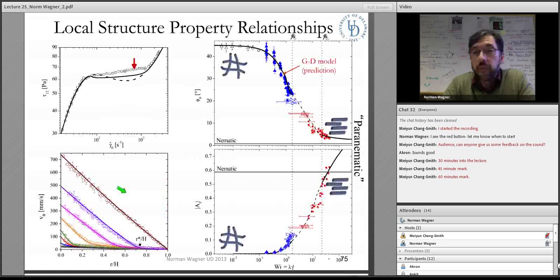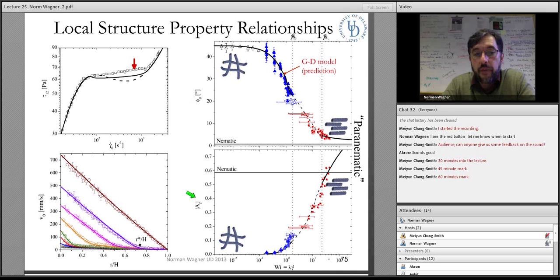Take that information for this state that I just showed you there, which corresponds to this velocity field, and I could calculate the angle now and the alignment factor as a function of the actual shear rate locally, because I have the local shear rates, which are the derivative of these plots over here, and I have the scattering that corresponds to those local shear rates now. And what we find is two things. One, a rheology model that fits the actual rheology fairly well, does an excellent job of predicting what we should see in the neutron scattering.